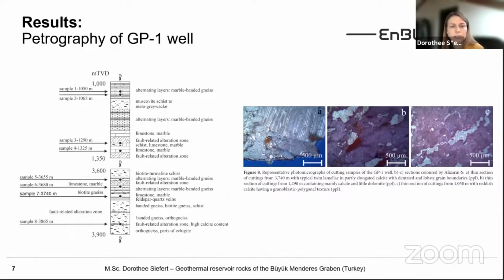And then the shallow marble horizon at a depth of approximately 1,000 meters to 1,300 meters is located above a fault-related alteration zone with greenish clay. And the marble consists of mainly calcite, also little dolomite with bulged grain boundaries. It can be seen on the right thin sections. It has a bluish to light gray color here and a low to medium light transmission. So compared to the other cutting samples, this marble has the highest calcite content of up to 75 volume%.